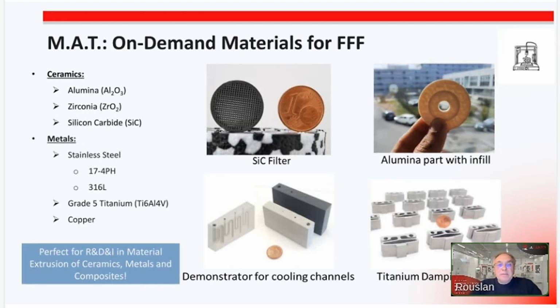Here, just the list, not an exhaustive list, of the materials we can process with this machine. So you see alumina, you see zirconia, but you see also silicon carbide. And this is really space-grade silicon carbide with a density over 97%. It's pure silicon carbide, not silica impregnated silicon carbide, so it gives some different properties.